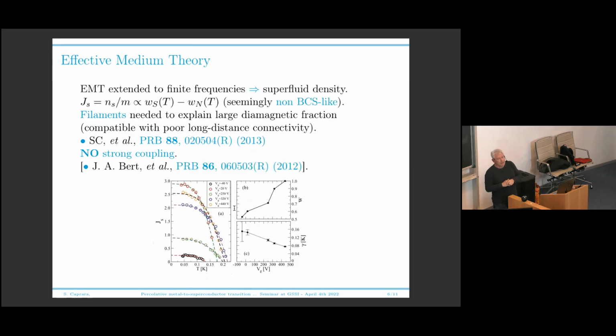Now, I will not go through the details, but you can extend the effective medium theory to finite frequency, because you know the metal to superconducting transition is very boring when you are in the superconducting phase, because in the superconducting phase, the resistance is zero. So there is very little to tell in the superconducting state if you study transport at zero frequency, because if you're running a current through your superconductor and your current is below the critical current of the superconducting state, then you experience a zero resistance, and that's all.